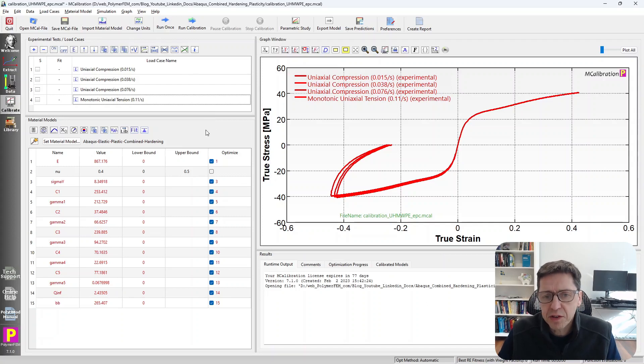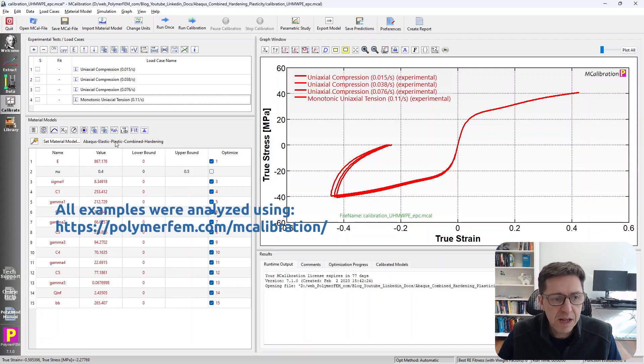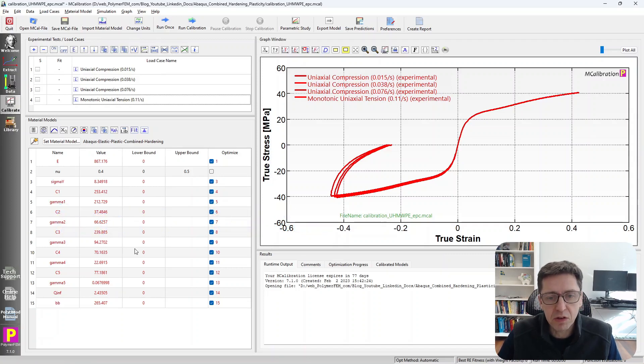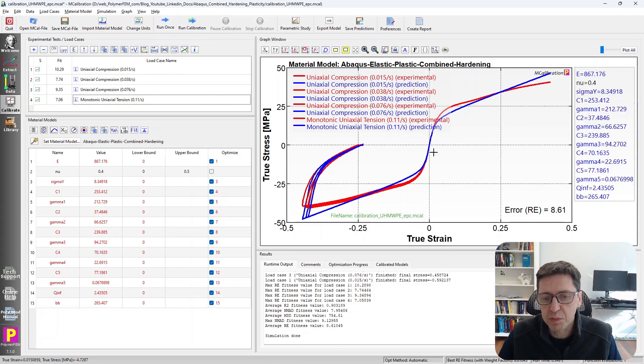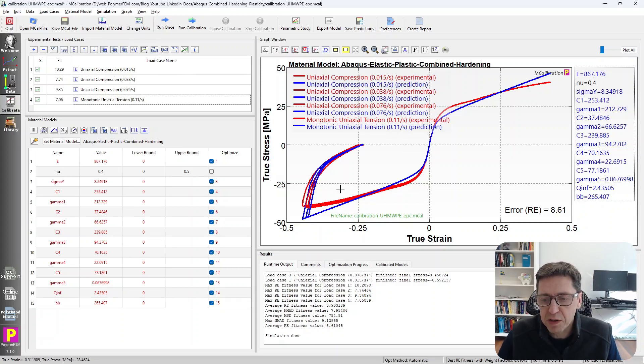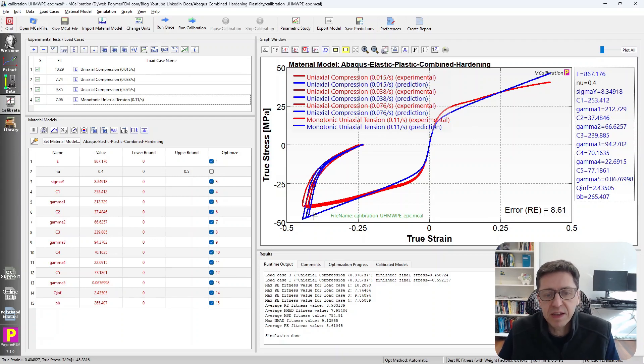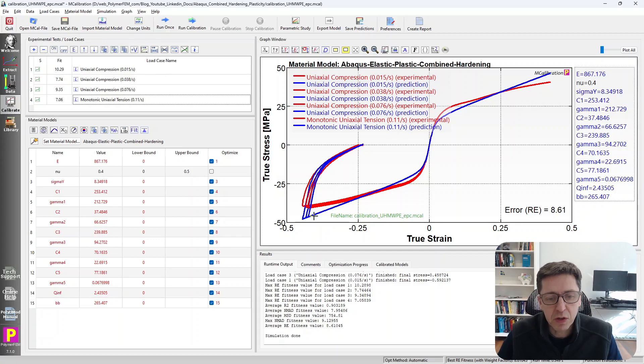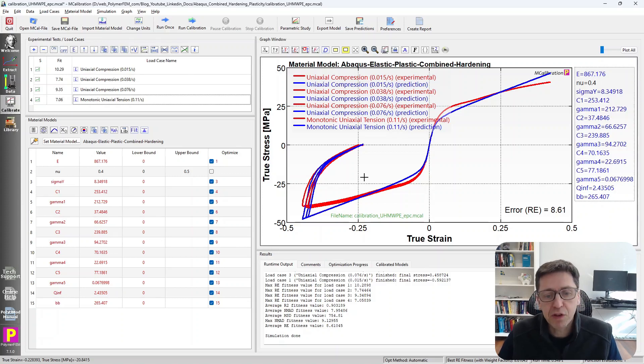To illustrate this in practice, here's experimental data for ultra high molecular weight polyethylene — experimental data in red, a tension test, three compression tests — and an Abaqus elastic-plastic combined hardening material model already calibrated in MCalibration. The predictions look reasonable: they capture the essence of the shape of these curves and represent the best overall fit I could produce. The details aren't perfect and there are some errors, but it's clearly more predictive compared to isotropic hardening plasticity, and is what I recommend for cyclic loading or polymer work generally.